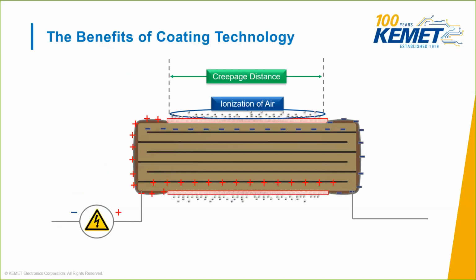Now, some capacitor manufacturers have turned to coating technologies like we talked about. Polymer or glass coatings are applied to the surface of the chip to fill those voids and provide a smooth surface with better creepage distance capability. Filling in these voids with insulating material also reduces the potential for the entrapment of contaminants and improves the dielectric stability across the surface of the chip.